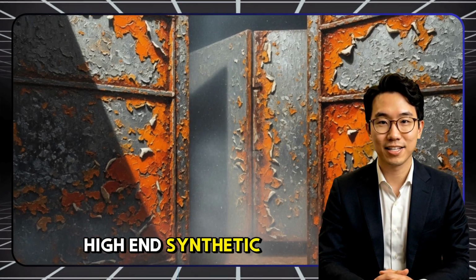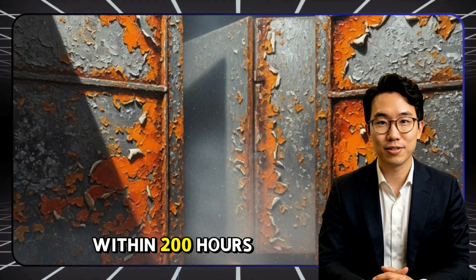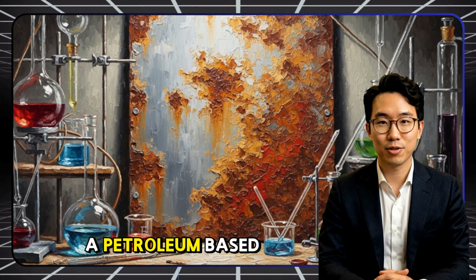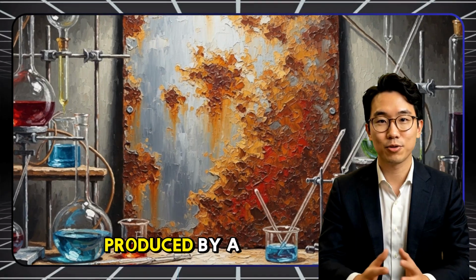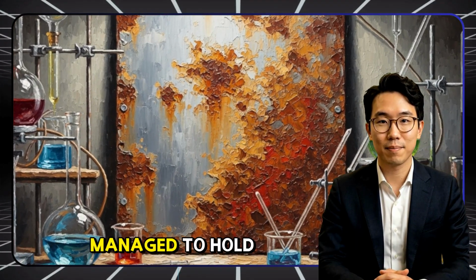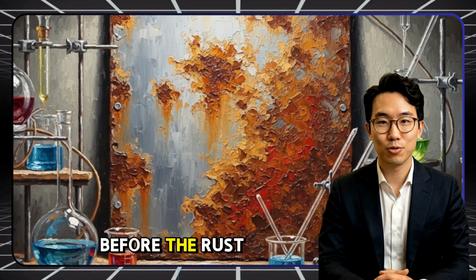Most of the high-end synthetic coatings of the time started to fail within 200 hours in those brutal chambers. The nearest synthetic competitor, a petroleum-based phosphoric acid primer produced by a major chemical manufacturer, managed to hold out for 600 hours before the rust broke through.